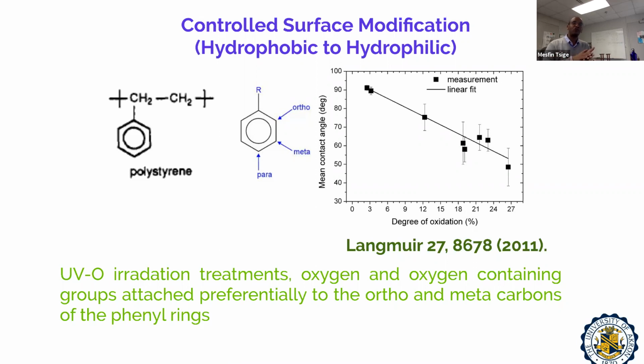And the benefit of this one is this change only happens in the top few nanometers. The rest of the polymer film doesn't change. Its mechanical properties, everything stayed the same, but the surface properties change. As a result, they were able to tune from hydrophobic to hydrophilic, going down to a contact angle of around 46 degrees.